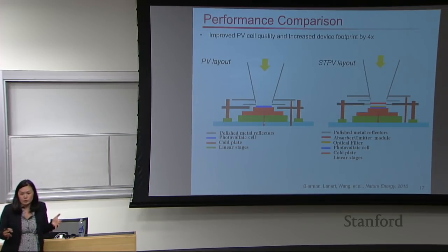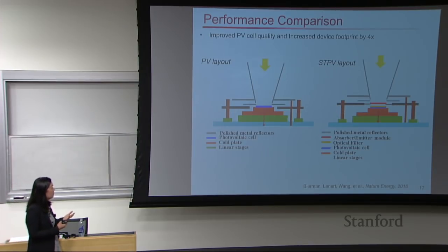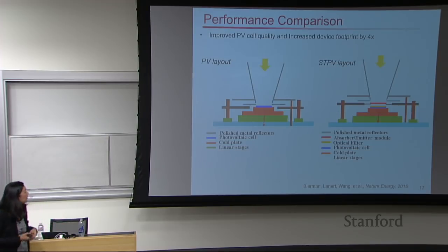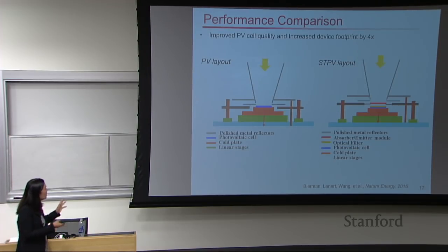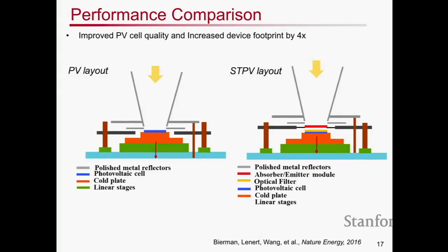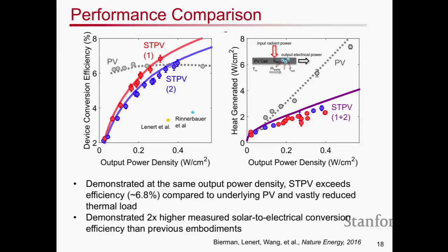And with that, you certainly have less parasitic losses from the sides, and that also contributed to the improvement in efficiency. So with this test platform, what we've been able to do now is really do a direct comparison between the conversion process with just a photovoltaic cell, and once we introduce the selective emitter absorber with this filter incorporated into an STPV system. And this is what we saw.